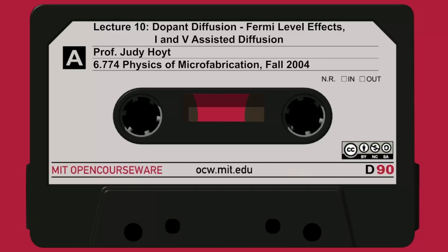The next sort of interfacial effect that I'll talk about is interfacial dopant pileup. Be careful. This is not equilibrium segregation. This gets a little tricky because we just talked about across an interface, the dopant concentration being different. This is actually piling up right at the interface. So it's a little bit different. It's a monolayer type effect. And particularly as junctions become shallow, it's observed that some of the dopants pile up in this very narrow interfacial layer at the interface between oxide and silicon. This pileup is separate from and is larger than the normal equilibrium segregation that might occur during annealing.